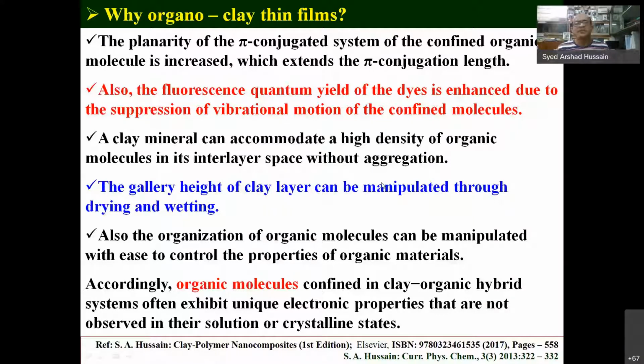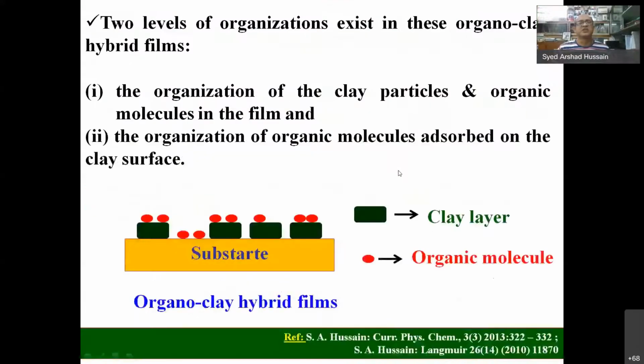And also one can place a lot of organic molecules within these systems without aggregation. One can play by controlling the layer thickness, gallery gap, etc. One can play with the organizations in a systematic way. Therefore, as a whole, the organo-clay systems show interesting optoelectronic behavior which may not be available in these single organic systems. Here is a cartoon I am showing: say this is a film of clay shown in black, and this is organic material. So on your substrate, clay, then organic material, again organic material may be on the clay surface or substrate also. So in this way you can play with the organizations and hence the optical or electronic behavior.